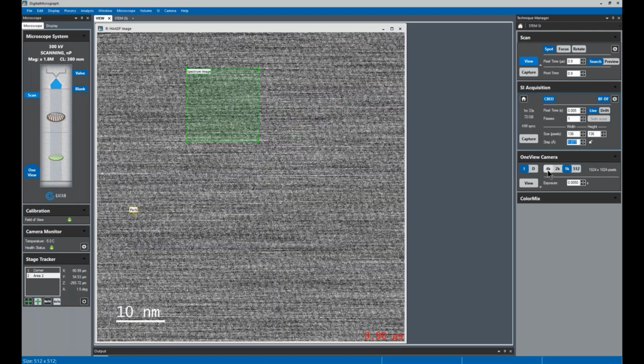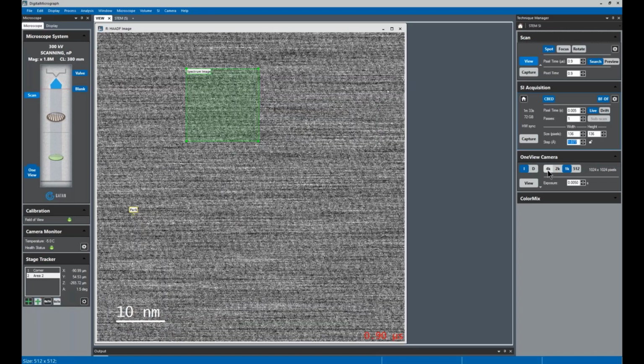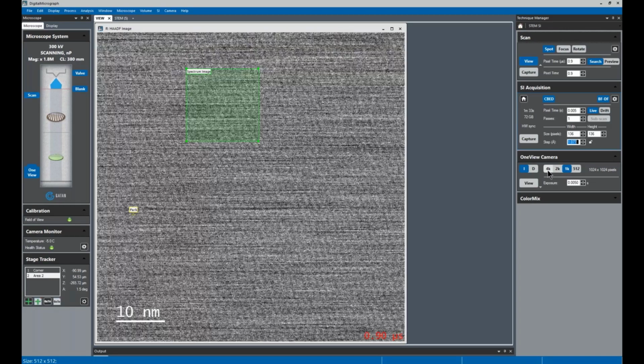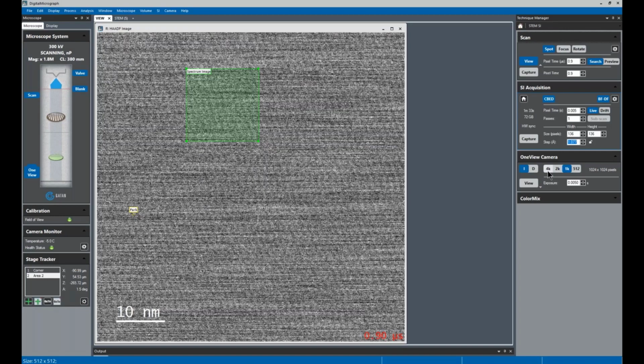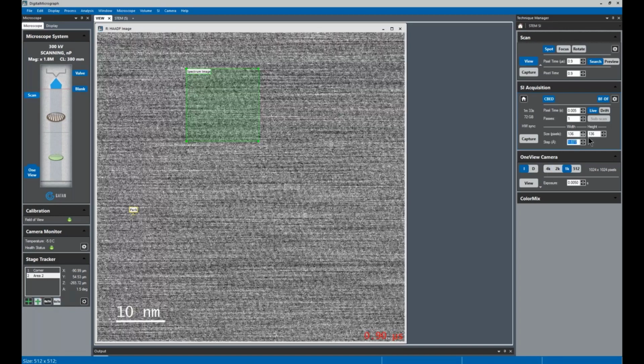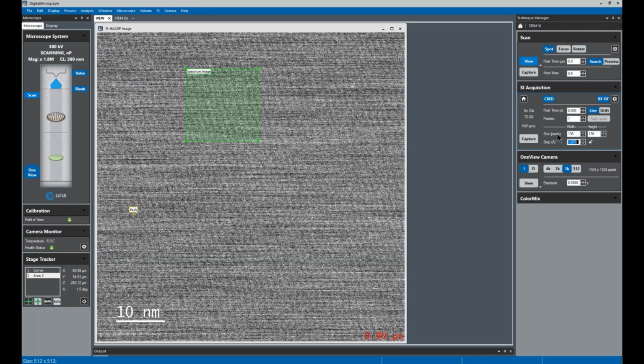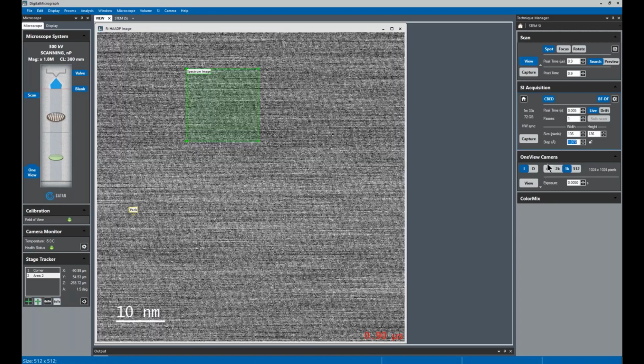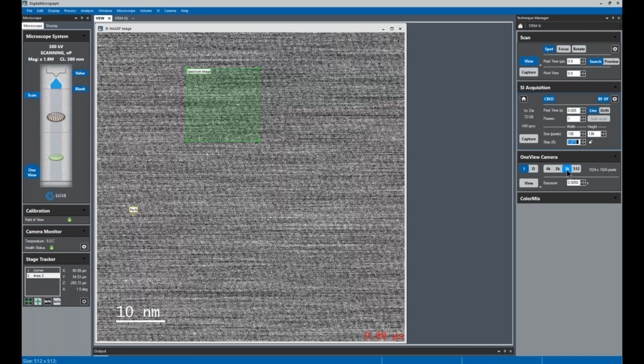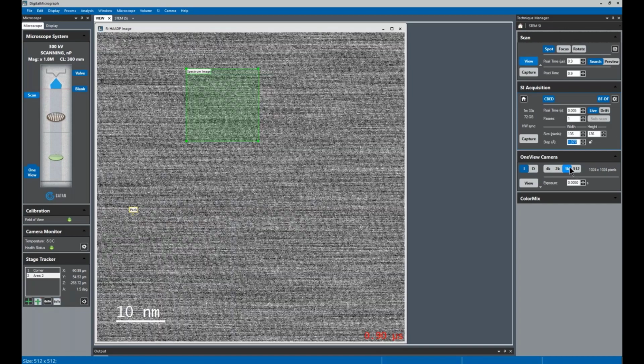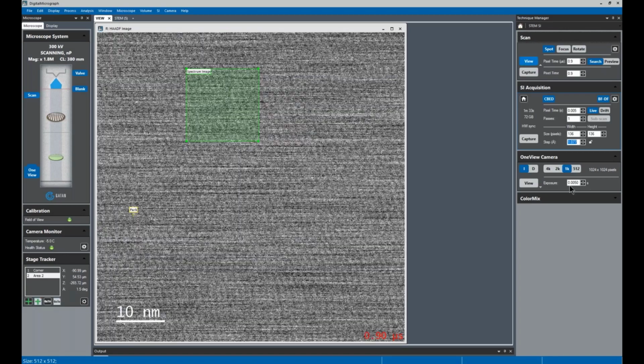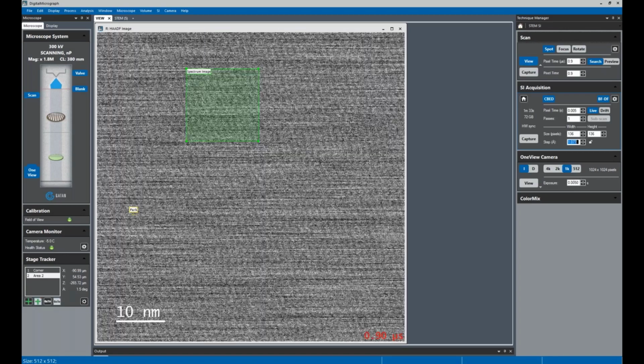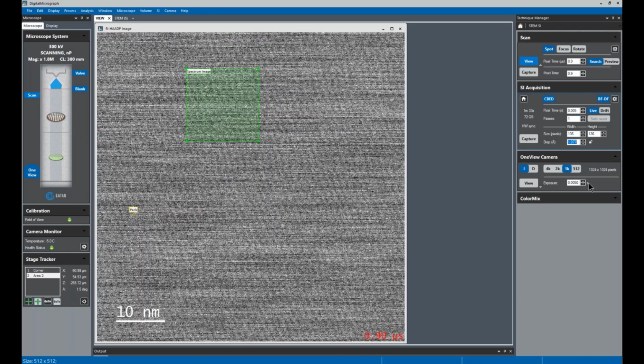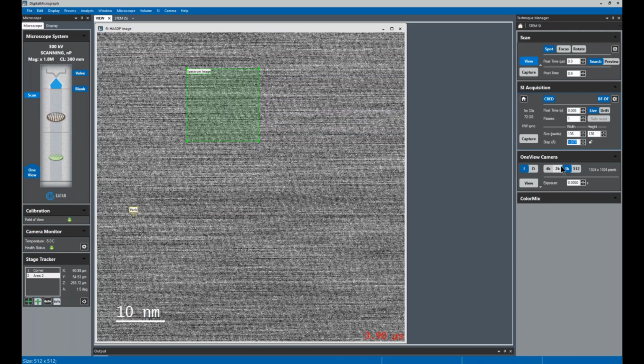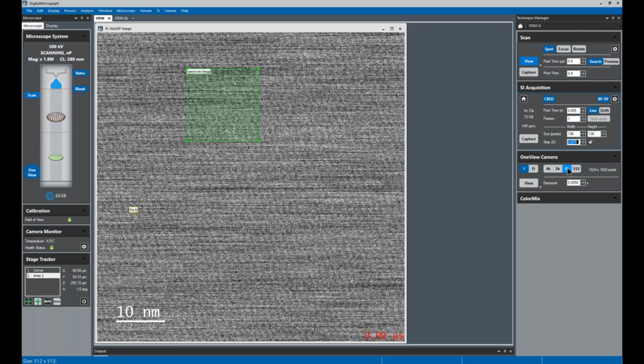Because if we were doing 4K by 4K imaging, we have 25 frames per second, so we'd only be going 25 pixels per second, and that might be too slow in many cases, especially if you have a big spectrum image in number of pixels that you're trying to collect. So if we bin down the image to 1K by 1K, our max frame rate at this binning is 200 frames per second, which is an exposure time of 0.005 seconds. Because the camera's the timing master, it's essentially the rate-limiting step in the signal flow, so binning down the image is a good idea to enable us to go faster.